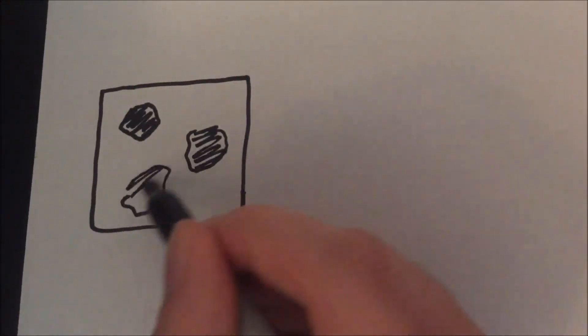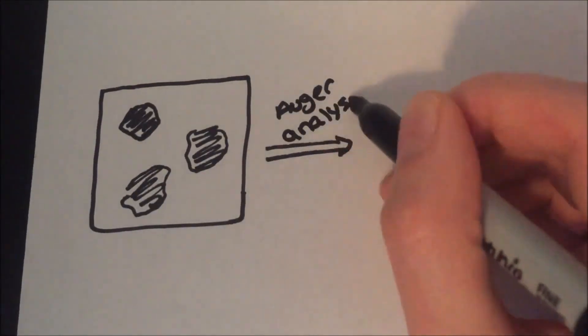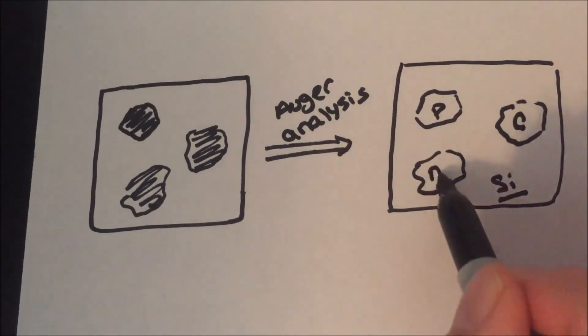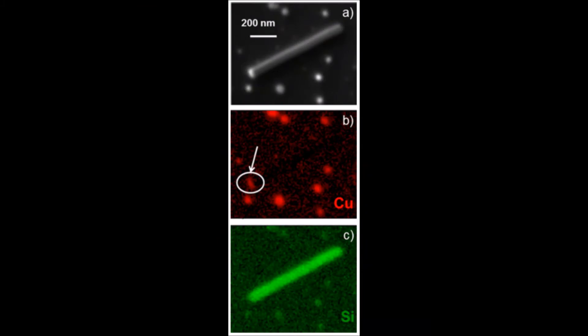Through this technique, multiple elemental domains within the first few nanometers of the sample surface can be mapped out, yielding elemental information to correspond with the image generated by the SEM.